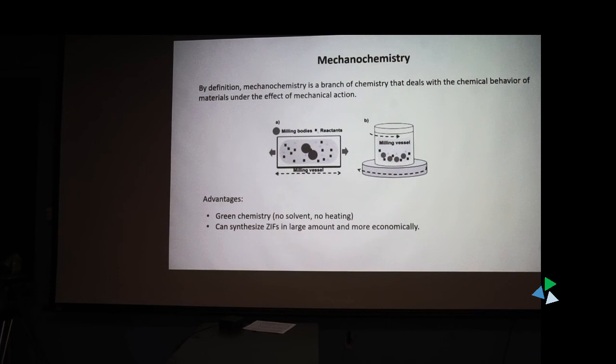Mechanochemistry is getting more and more popular. The advantage is that it's green chemistry. You don't use any solvent. Everything is dry. And there is no heating. It's done at room temperature. And also, from the point of view of ZIFs, you can synthesize many great varieties of ZIFs at a cheaper cost, very cheaply.